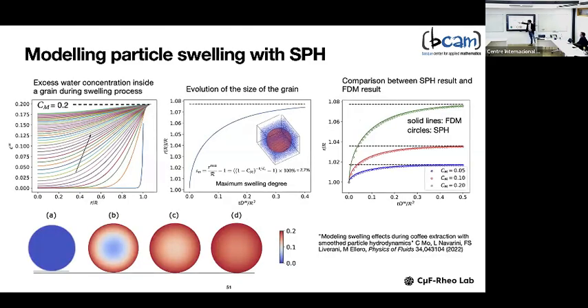This is more or less what happens. This is the concentration of water inside the solid. This is the surface. This is the center of the coffee particle. At time 0, you have essentially a value here that we prescribe as a boundary condition, and then essentially 0, the particle is dry. Then eventually this water diffuses inside the solid, and at the same time the size of the particle increases, and we can tune the maximum swelling ratio by simply imposing different boundary conditions here for